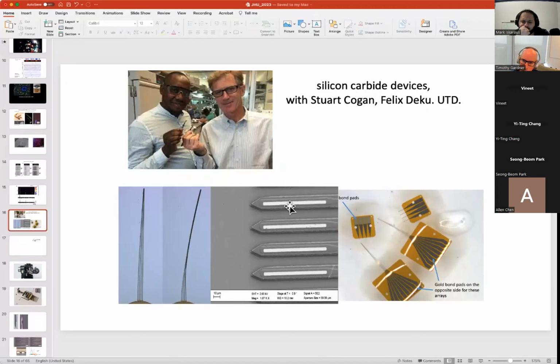They're silicon carbide, which is one of the very few materials that the body doesn't appear to degrade upon implant. So the longevity of these with chronic implants and accelerated aging looks really good. And we think that they could be particularly useful for stimulation in cases where you need really small scale stimulation for therapeutic purposes with high channel counts. So if that's of interest to any folks here, I'd be really happy to talk further.